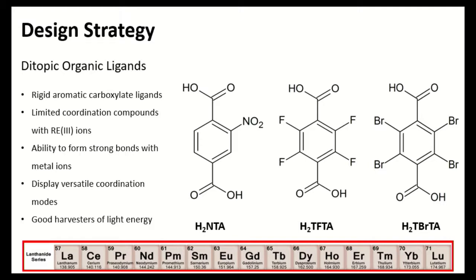Our design strategy is to use ditopic organic ligands. These are the ligands that we use. They are different forms of terephthalic acid that have different functionalities connected to them. First we seek to use similar ligands where the functional groups are different. As Zayar spoke about, initially we sought to do some form of serendipitous synthesis. But it is only in doing these kinds of syntheses and making more compounds that we can then do a sort of retro-synthetic analysis to identify the conditions that would lead to the formation of particular frameworks.